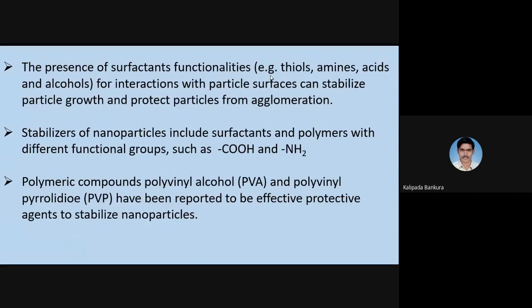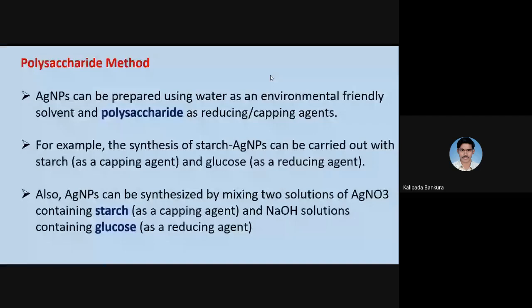Agents of surfactant functionalities, that is thiols, amines, acids, and alcohols, for interaction with the particle surface can stabilize particle growth and protect particles from agglomeration. Stabilization of nanoparticles includes surfactants and polymers with different functional groups such as carboxylic acid, and different types of polymers, that is polyvinyl alcohol and polyvinyl pyrrolidone, were also reported as stabilizing agents. In the polysaccharide method, silver nanoparticles can be prepared using water as an environmentally friendly solvent, and polysaccharide is used as both reducing and capping agent.